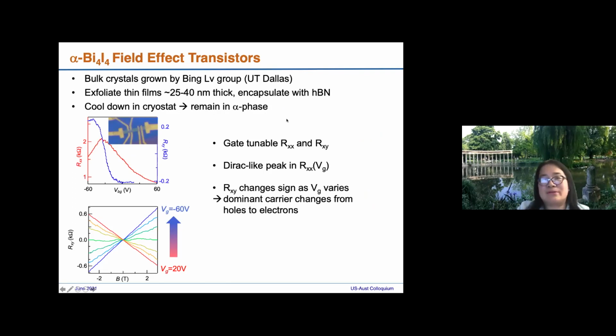We encapsulate them with hexagonal boron nitride because this material is air sensitive. It's not too bad, but they do degrade if we leave them out in air for, say, more than a few hours. We just naturally cool them down in the cryostat. The alpha phase is a natural low temperature phase, so we did not do any quenching. This material is expected to remain in the alpha phase.